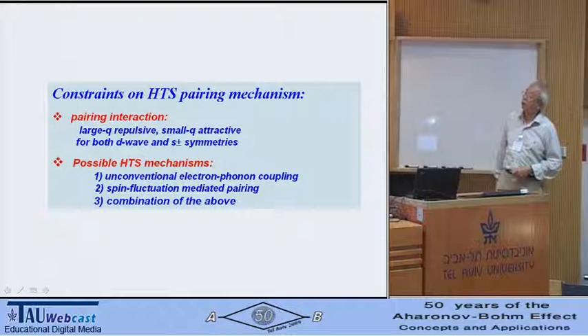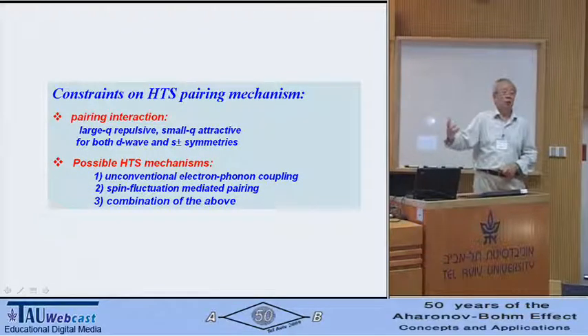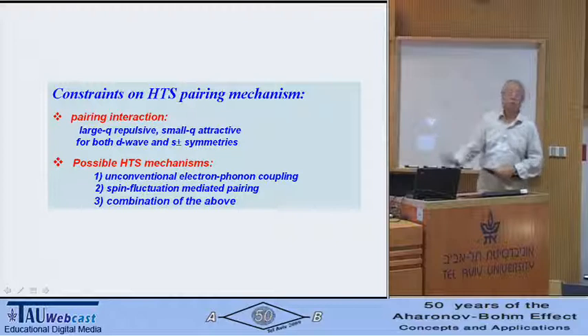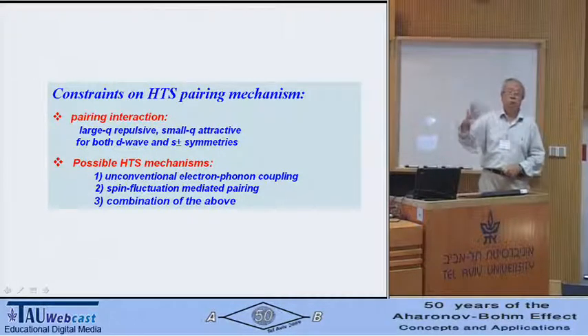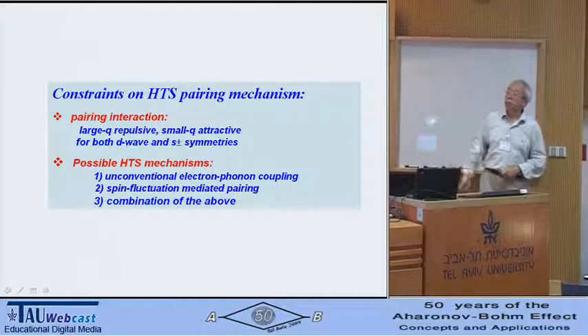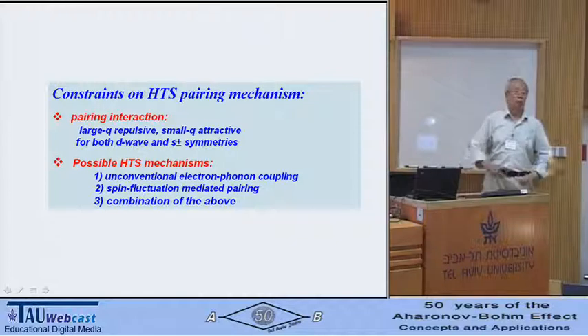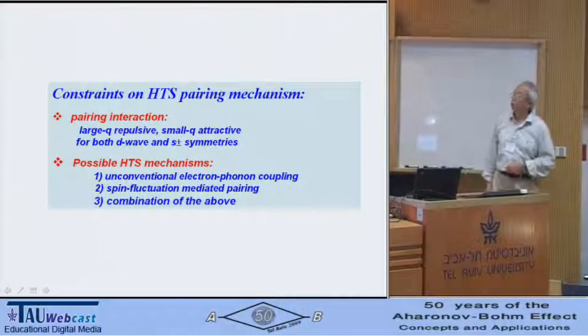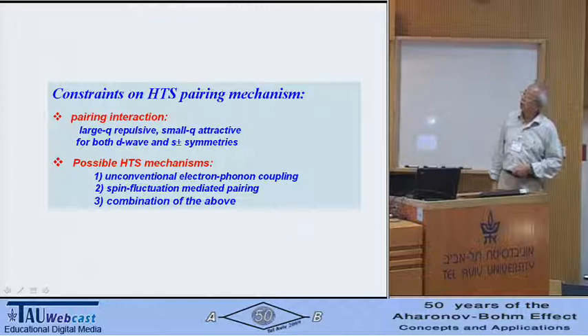Now, what are the possible high temperature superconductivity mechanisms? I would say if it's electron phonon, it has to be unconventional. Why? Because some theoretical calculations indicate that a regular electron phonon coupling simply does not support high TC in this system. So if anything, it has to be a specialized phonon, anharmonic, nonlinear coupling, and so on. I did some work along these lines recently.